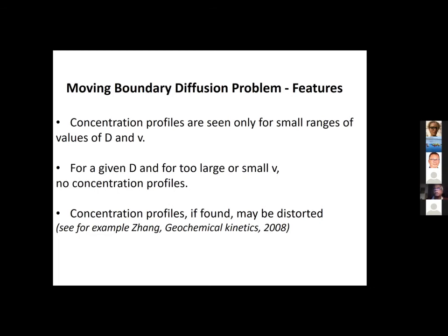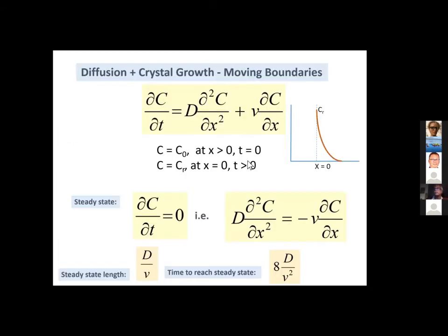Now, it gets even trickier than that. So that was the equation. Now, if you have that equation, you can go and set the change of concentration with time to be 0, a steady state. You don't have any change going on. What that means is, again, what Tommy was saying in words, your diffusion flux has to balance the flux occurring by growth and dissolution.